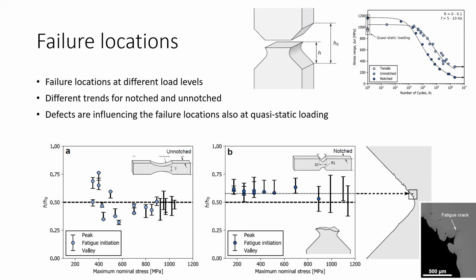And what we see is, of course, for the unnotched, we have the large scatter and fatigue, while the fracture surfaces are ranging across the minimum cross-section for static loading. And the same is seen in the notched. We have failure initiating from the defects in fatigue and then ranging across the minimum cross-section in static loading.